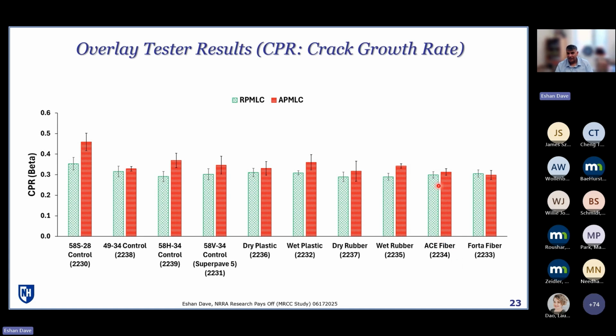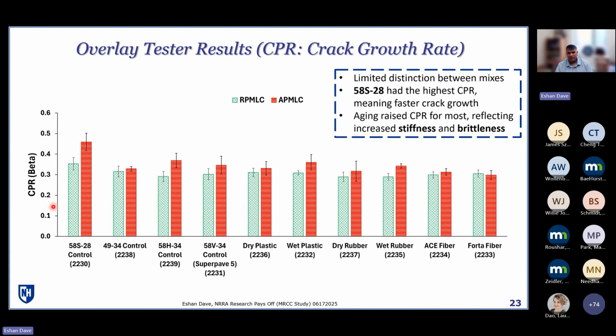And that's why you are seeing this relatively flat value with low CPR values. With more of your traditional mixes, you start to see them creep up as you go through aging. And once again, the control was the one with the lowest performance, or the highest crack growth rate, as we saw with other tests.